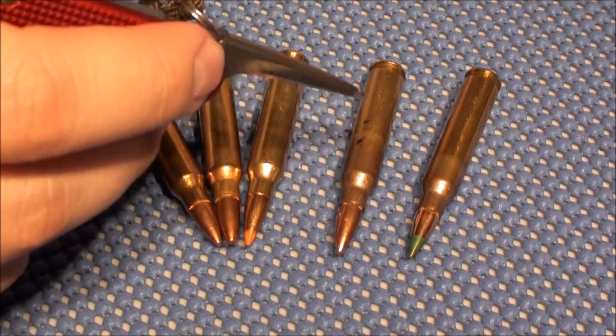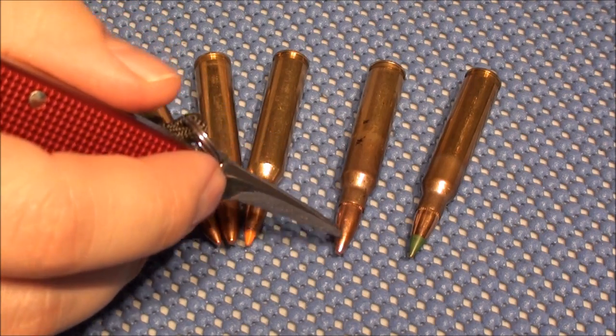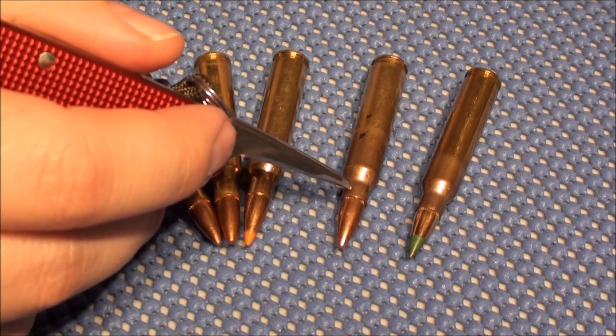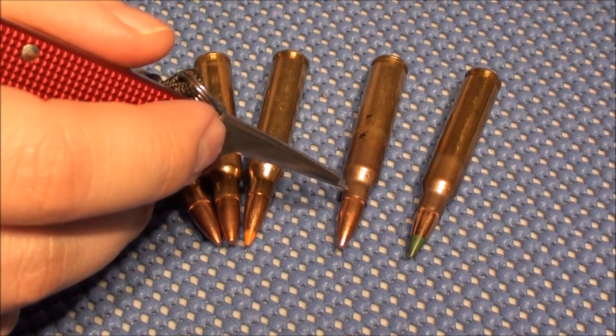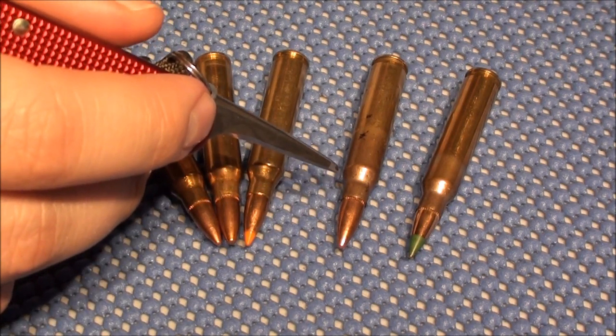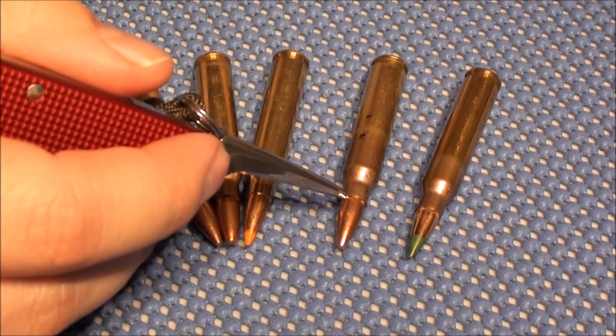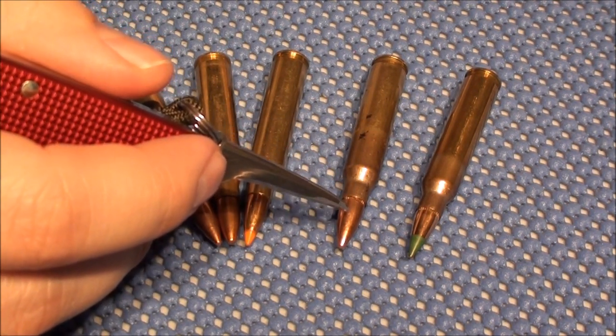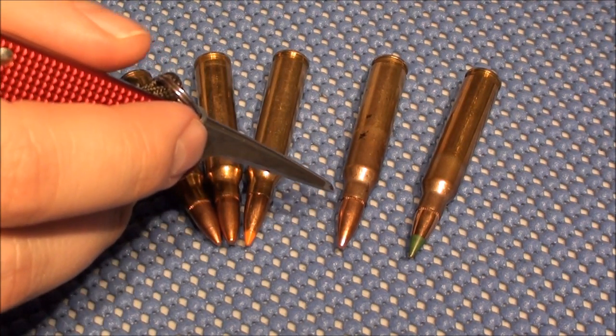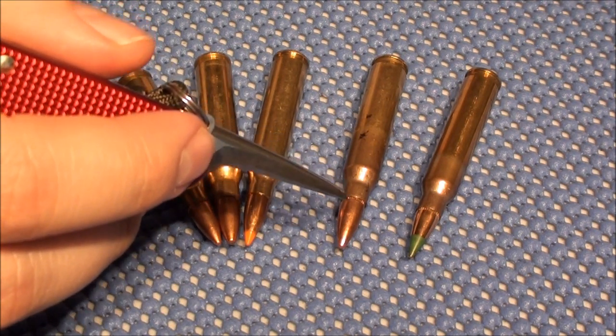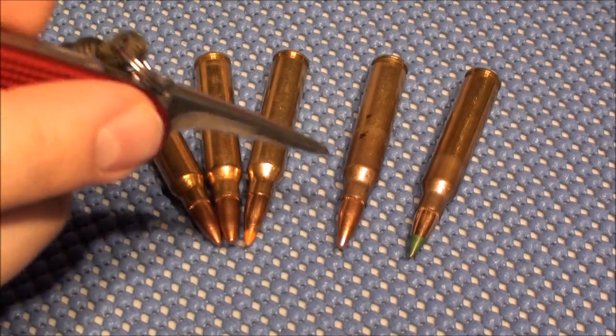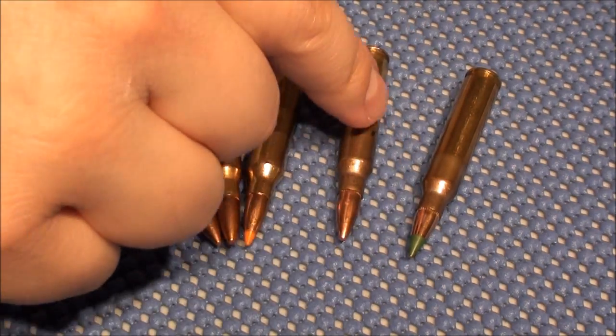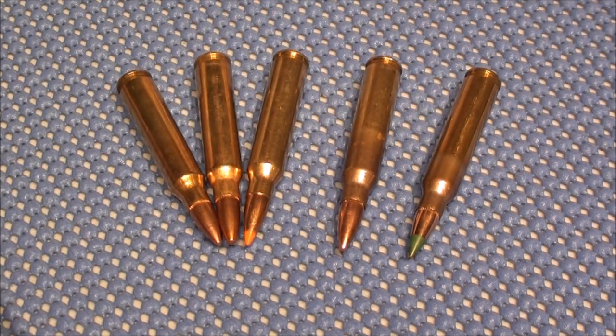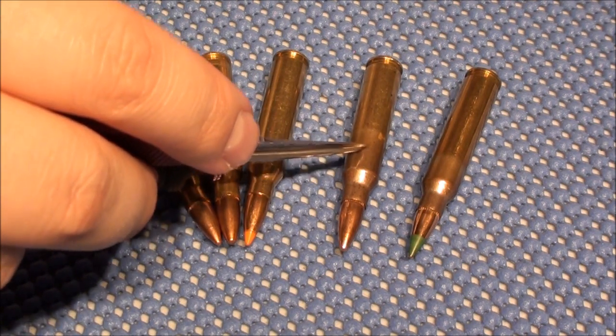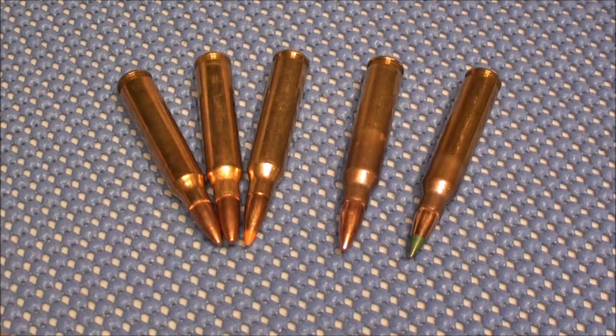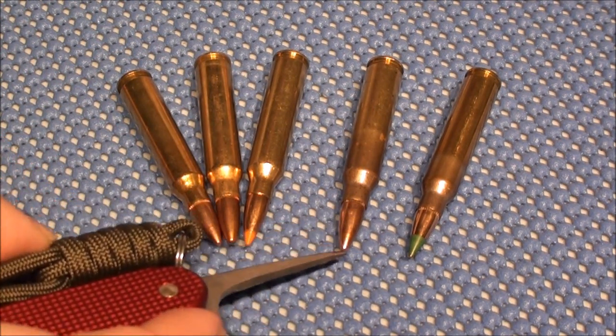Now, from everything I've read, the M193 will have greater probability of fragmentation when the velocities are over 2,700 feet per second. Now, out of a 16-inch carbine length barrel, that velocity is usually seen from muzzle to about 150 yards. Past that, the bullet drops below 2,700 feet per second, and therefore the reliability of fragmentation actually goes down. The other thing that I like about it is the brass tends to be higher quality in the M193, so for reloading, it's actually a little bit better from what I understand. So anyway, that's a little bit of something about why I chose the M193.